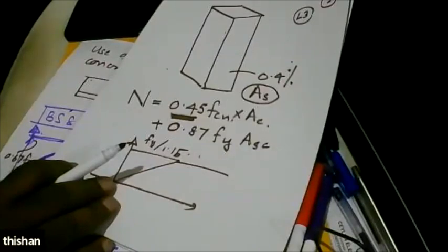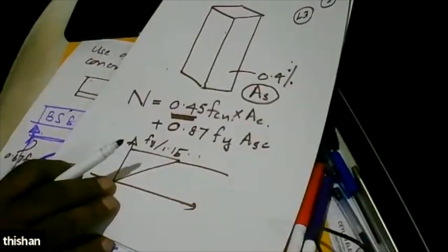It's very difficult, sir. Yeah, but they have to understand, because all our calculations are correct not at 20% or 30% strength. If we cure it and achieve the desirable strength, and for that, modern cements need about 7 days of curing. That's why we are proposing that we use at least 10 to 20% fly ash. A minimum of 10% fly ash will make sure there's enough material in it. So whatever calcium hydroxide is produced, the reactions can take place later, gradually, where the fly ash starts reacting with the calcium hydroxide produced as a result of the curing process.